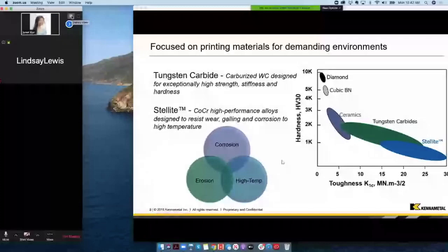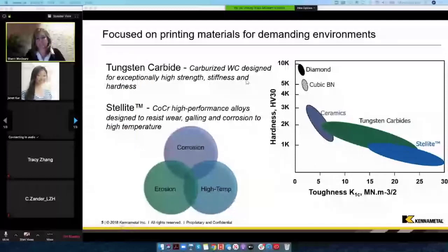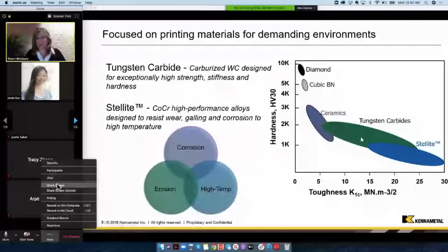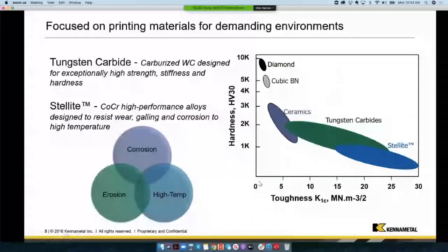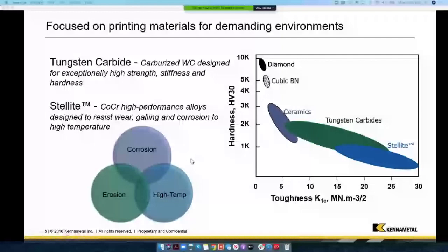And if you look at this material map of a couple of key performance attributes for these types of materials, toughness on the x-axis, hardness on the y, you can see where tungsten carbide falls in the green and in the blue. There are several grades of tungsten carbide and several alloys in the Stellite family, and they're getting up into the range of, in some cases, what you would get with ceramics. So we're talking about very hard, very tough materials. The Stellite is a cobalt chrome based material, and the tungsten carbide is basically a metal matrix composite where you have your tungsten carbide dispersed in a matrix of cobalt, or cobalt in combination with other metallic materials.